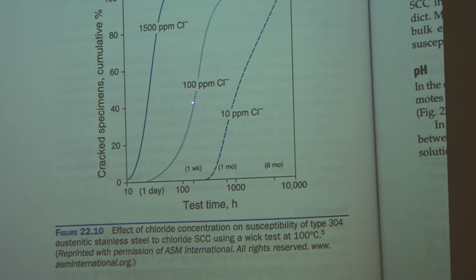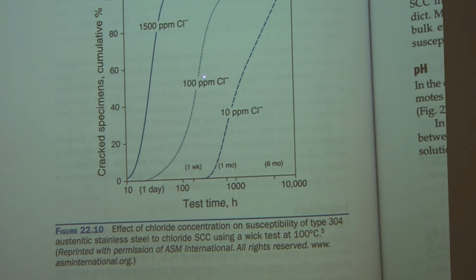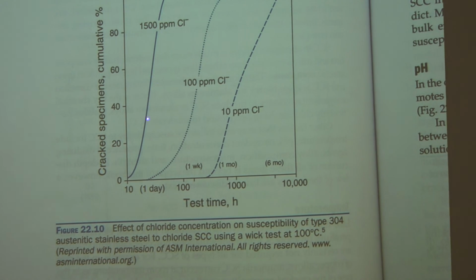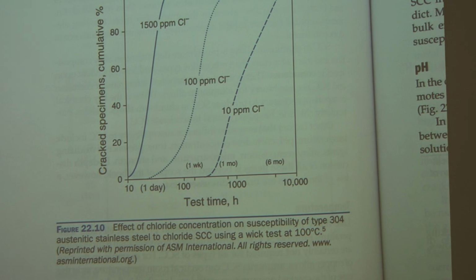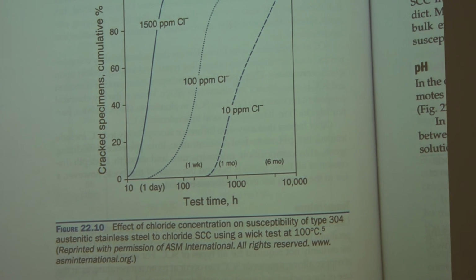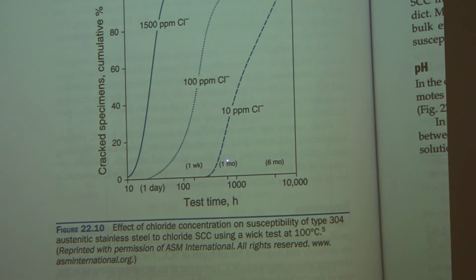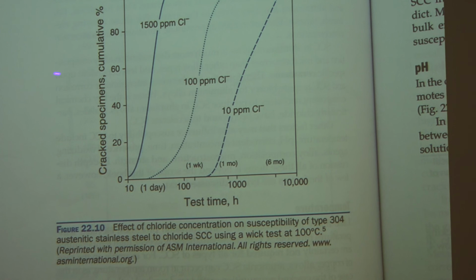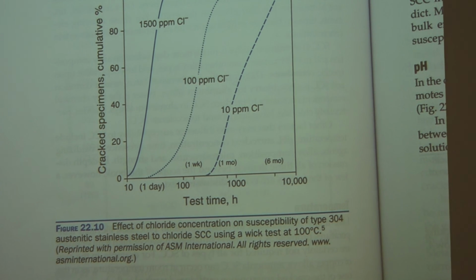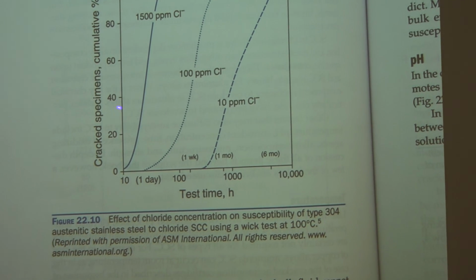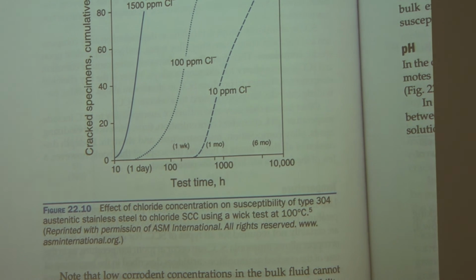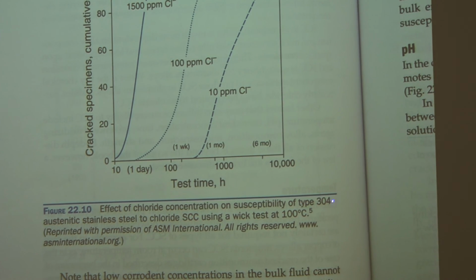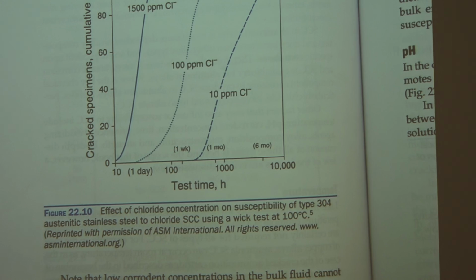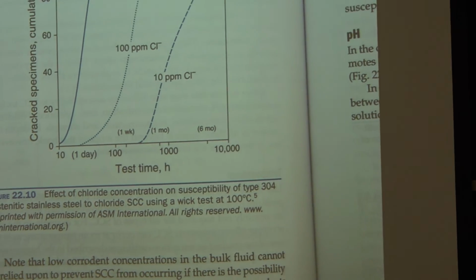100 parts per million chloride, you're getting to the EPA drinking water level. 1,500 parts per million chloride, we're getting into the brackish water area. And obviously seawater is like 30,000, but you can see, test time, this is a log scale. So your stainless steel, this actually is our hot dog cooker, in a sense. Lots of chlorides in those dogs, and 304 just couldn't cut it at the high chlorides and failed within days.